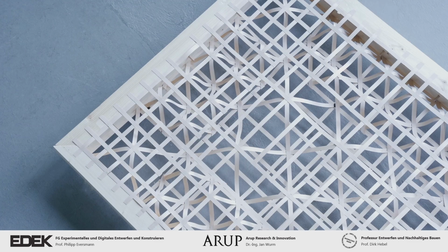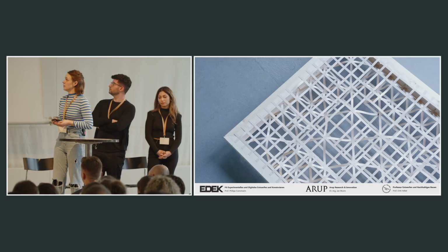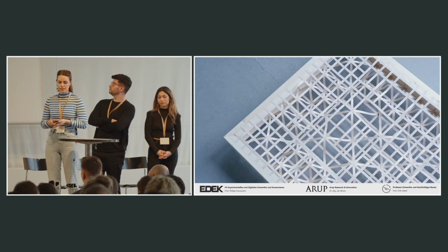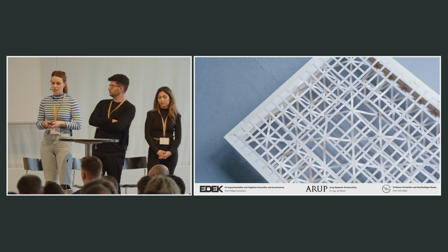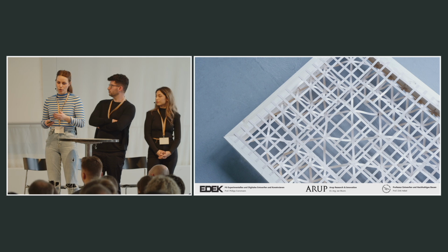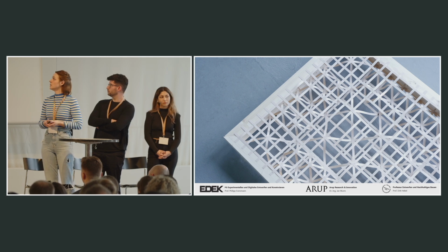We developed this strategy based on previous research, which has identified that the fundamental limits to the application of mycelium-based composites for large-scale architectural components are based on, as mentioned, poor tension and bending resistance properties. And the low tensile strength is largely due to the lack of longitudinal elements that can then transfer the loads across the component.